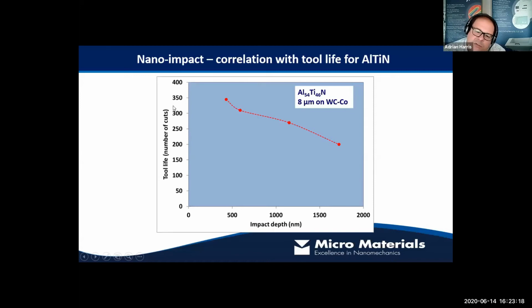Some cutting trials have been carried out. These are real cutting trials, and what they're looking at is the number of cuts they can perform under certain conditions before the wear on those cutters is deemed excessive. So this is real cutting results, and here are the corresponding nano-impact results. What we use as a metric in our nano-impact test is typically the depth of the probe at the end of the impact test. What we see here is a relationship between a small impact depth and a long tool life.